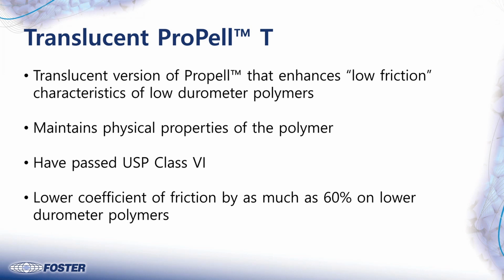Again, USP Class 6, and we're going to see from some of the data, you can lower the coefficient of friction of a very sticky polymer, which are the low durometer Pebax, low durometer polyurethanes, Pellethane trade name, quite significantly. You'll see that even some of the stiffer polymers like a nylon 11, nylon 12, which is reasonably lubricious, you can improve the lubricity of that. Adding some of these lubricants can also aid in the extrusion process and help out with manufacturability as well.